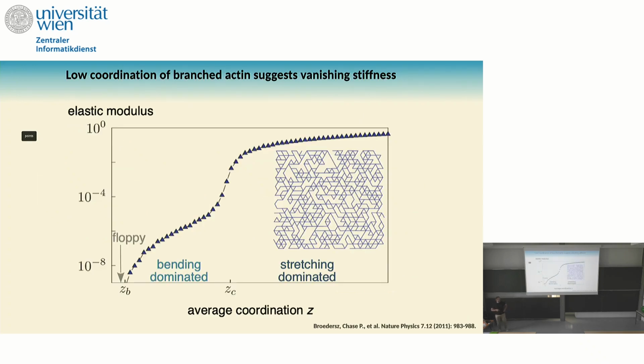So you can do your favorite model on lattice. You take, for example, a triangular lattice. You put your springs, and then you put bending between your springs and stretching as well. And you vary the coordination number by depleting more or less numbers of your bonds. So if you vary the coordination number and you measure the elastic modulus, indeed you find that there is a well-defined transition at some critical coordination number where the system starts to be rigid, but it's dominated by the bending. And then you have a second one where the stretching starts to dominate.